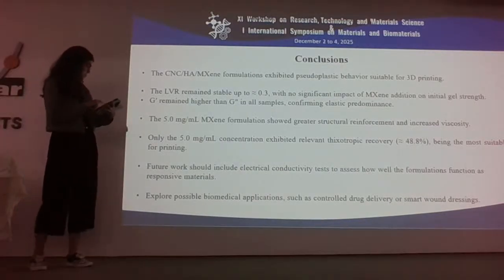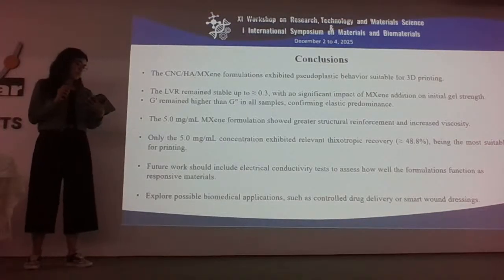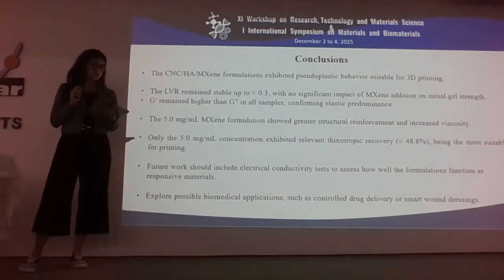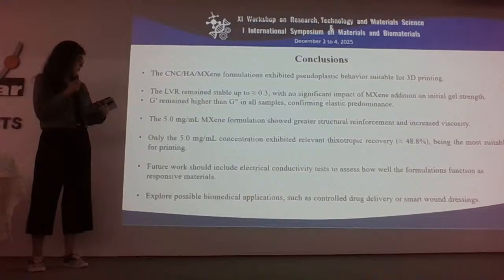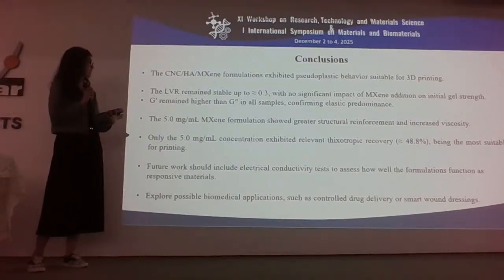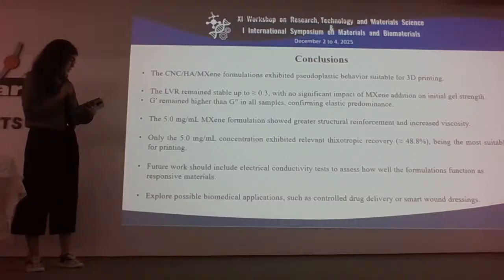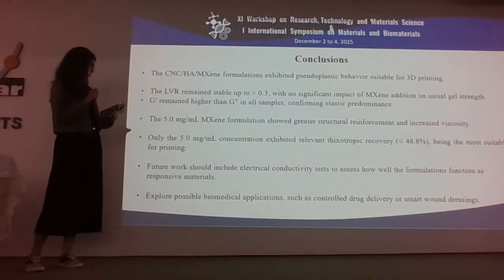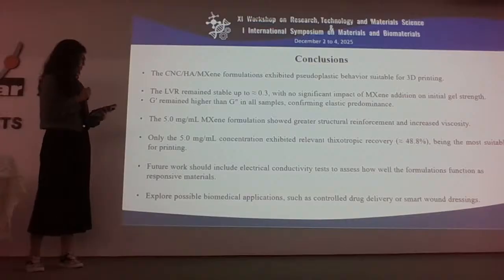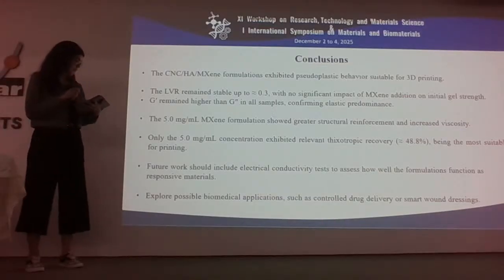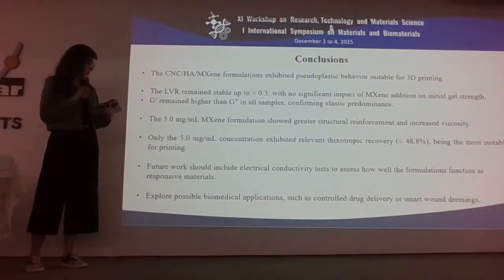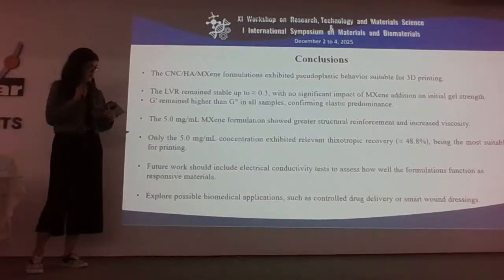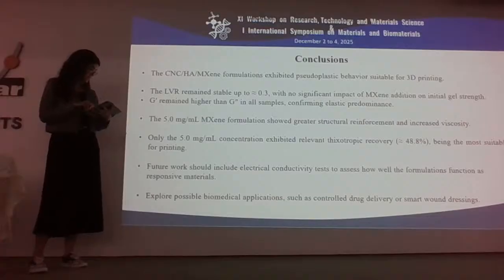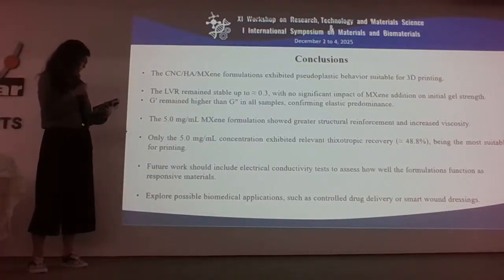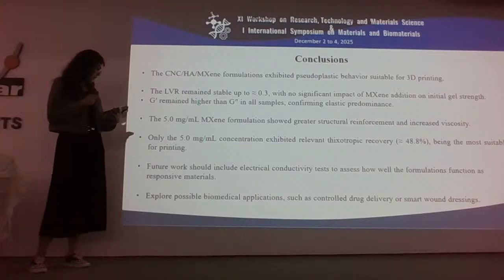In conclusion, the formulation exhibits pseudoplastic behavior suitable for 3D printing. The linear viscoelastic region remained stable. G prime remained higher than G double prime in all samples, confirming elastic predominance. The 5 milligram per milliliter MXene formulation showed greater structure, reinforcement, and increased viscosity. This concentration exhibited relevant thixotropic recovery, being the most suitable for printing.